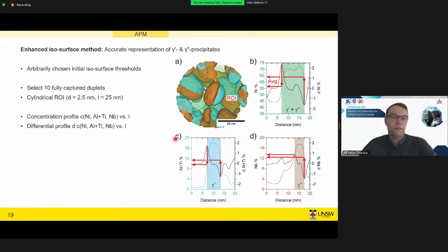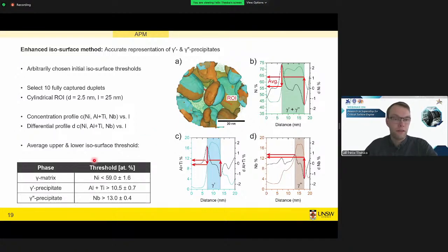Now we can plot a differential concentration profile, which tells us the difference between each step for this concentration profile. And what this tells us is the point of the highest concentration gradient, which should be the particle matrix interface. And you can see this works really well. We get global maxima and minima and can use them now as a threshold to accurately represent our particles. And those are the values I acquired for up to 10 particles here for the gamma matrix. For the gamma prime precipitates it is about 10.5 atomic percent aluminum and titanium, and gamma double prime precipitates is anything larger than 13 atomic percent of niobium.